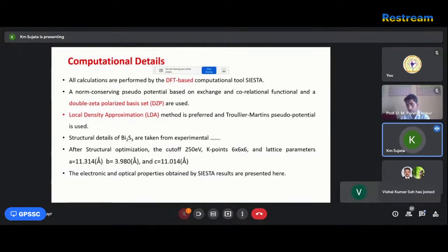Structural details of bismuth sulfide are taken from experimental results. After structural optimization, a cutoff energy of 250 electron volt is used, with a k-mesh of 6 by 6 by 6, and the lattice parameters are a equal to 11.314 angstrom, b equal to 3.980 angstrom, and c equal to 11.014 angstrom. Because the structure of this material is orthorhombic, the electronic and optical properties obtained by SIESTA are presented here.